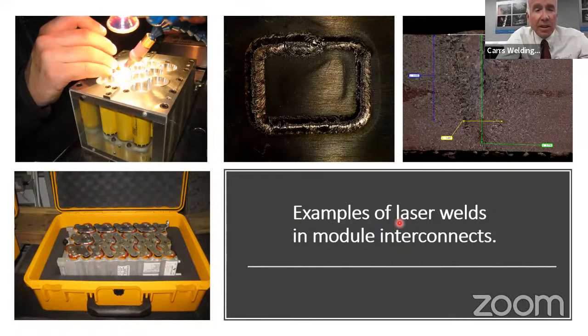So this is very typical of the sort of thing you'd see in my shop today. On the copper, on this circular, there's this weld here. As you can see, the weld gets bigger as we come around, because the preheat from the weld where it started put a bit of heat into the job, so it looks a little bit bigger at the end. We start here. Now that is actually 10 mil across here, so it's quite small. And it is copper, although it doesn't look like it. That is the cross section: two bits of material, 2 mil thick, in the bus bar system that we're making here. That gets too hot to be a cell weld, but it's a really good connection for a bus bar interconnecting system.